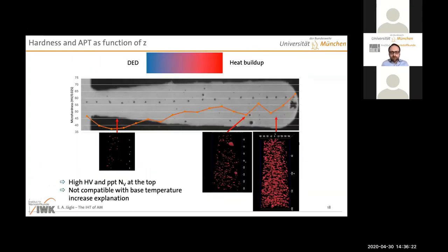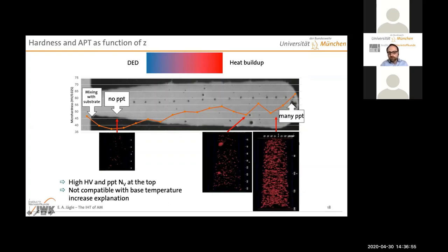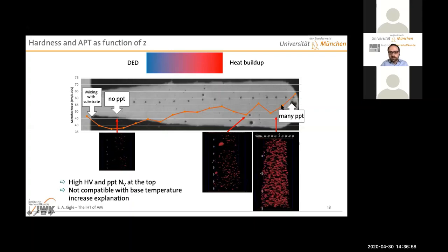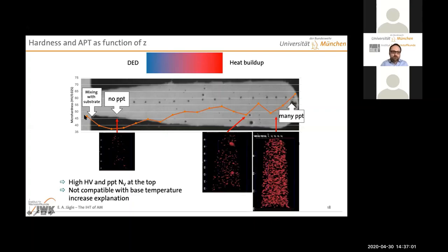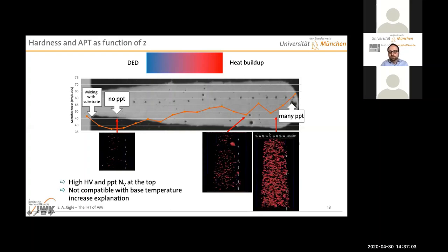This here is the hardness profile across one of these thin walls. And you see again that it is very soft at the bottom and hard at the top. So again, immediately we can rule out that the peak-like reheating is the key point in this case. So just the opposite of what we found in our very early study on maraging steel. Here the top is hard and does not show this drop. Okay, so you see here again with atom probe tomography that we have lots of precipitates in the very top few layers, basically nothing at the bottom. Here we have a bit of a mixing with a substrate effect that we can ignore.